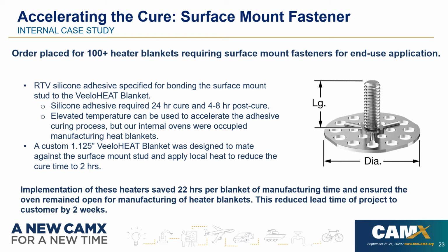We initially demonstrated this with just our ovens, but soon realized that we really preferred to use our ovens for manufacturing the heat blankets. So we did an internal case study on a custom 1.125 inch diameter heat blanket, designed to mate against the surface of the stud and then apply heat locally, again achieving a reduced cure time of only 2 hours.